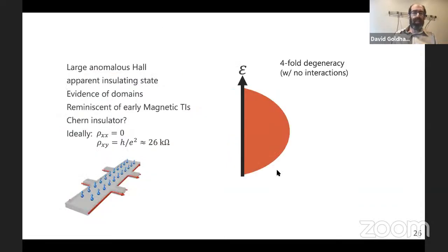So what's going on with this magnet? The clues that we have are that there's a large anomalous Hall signal. Anomalous Hall signals have long been seen in ferromagnets, and normally they're milliohms or maybe ohms at largest. In this case, they're much larger than that, but they do diagnose magnetism. There's apparently an insulating state there. We see domains. This all looked a lot like earlier in the 2010s magnetic topological insulating films based on bismuth telluride. And so that suggested to us maybe what we were seeing was a Chern insulator, an equivalent of a quantum Hall system, but at 0 magnetic field.